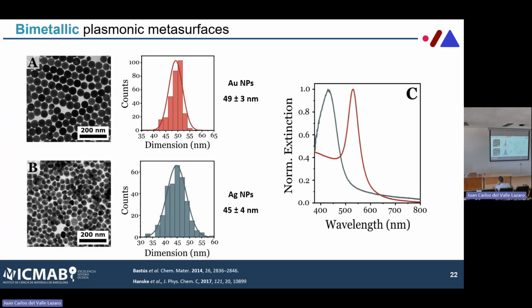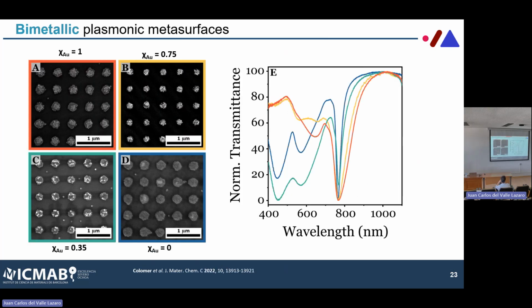In the second work that we did, the idea was, okay, let's try to exploit this. Now that we know this, how else can we modify the internal structure of these cluster arrays? One thing that we thought, in a work that we did with a master's student, was let's try to mix particles together. So we synthesized gold and silver nanoparticles. In this case, they were quite big, 50 nanometers. The motivation for that will become clear a little bit later in a few slides. But basically, we just synthesized the two colloids and then we co-assembled them.